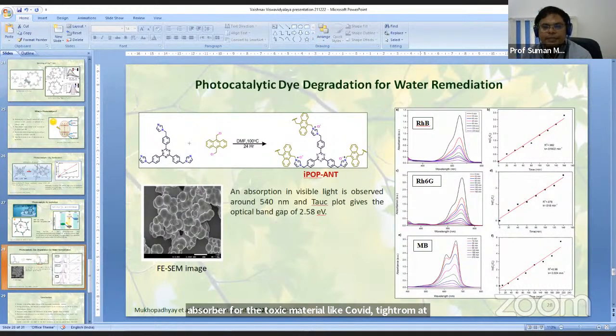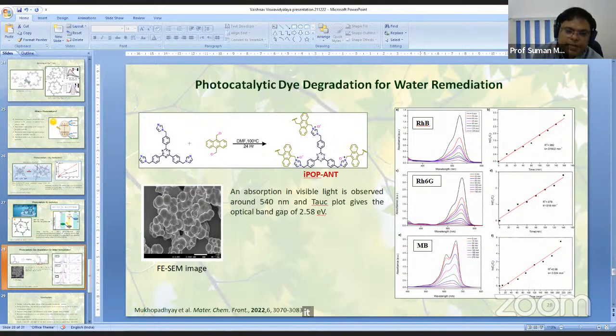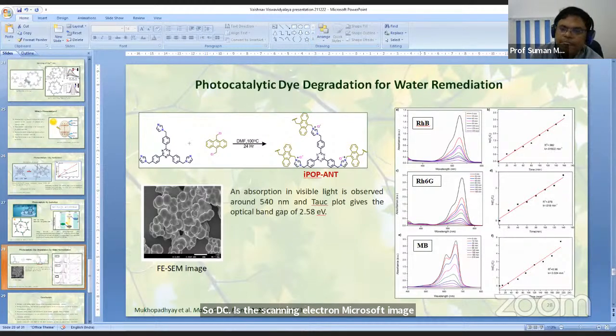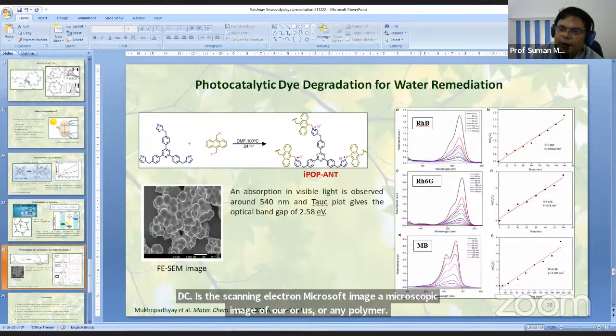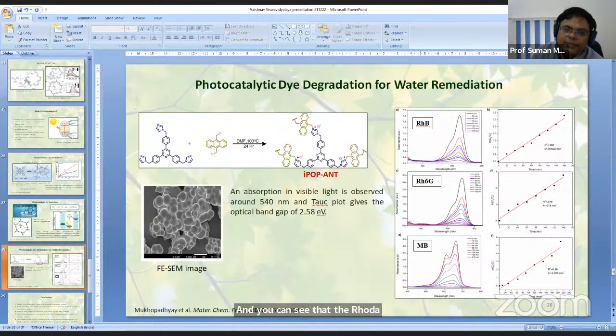So I am not showing that here, but rather what I am showing is that this particular COF or porous organic polymer can absorb visible light in the range of 540 nanometer, which is equivalent to 2.58 electron volt, and that can be utilized for the degradation of different dyes. So this is the scanning electron microscopic image of our porous organic polymer, and you can see that the rhodamine dye can be degraded utilizing the photocatalysis of our covalent organic framework.